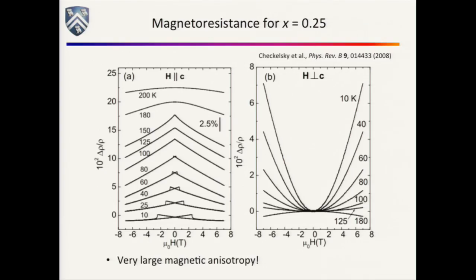OK, so here's what you get if you look at the magnetoresistance, the magnetotransport, at x equals a quarter. If the magnetic field is along the c-axis, you see some kind of little butterfly-shaped hysteresis loop as you go down in temperature. Right when you get through TC, the shape changes. You see this butterfly hysteresis loop developing. And the magnetoresistance, everything's multiplied by 100 here, so the magnetoresistance is on the order of a percent. Not very big.